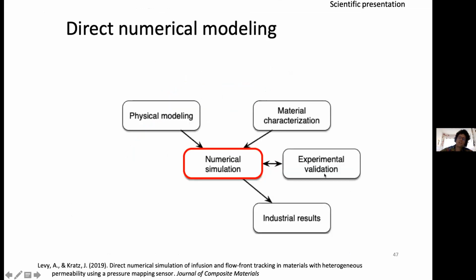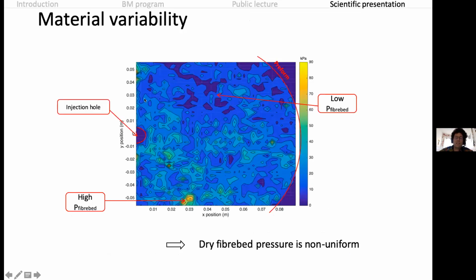Meanwhile, what I did when I was here was working also on the numerical simulation. The idea was to start with this random distribution of pressures that is representative of your material, and try to account for the fact that this high pressure here means that there's more fiber, so it's less permeable. Whereas here there's less fiber, so the resin is probably going to flow more easily. The flow of resin is going to be easier here than there.